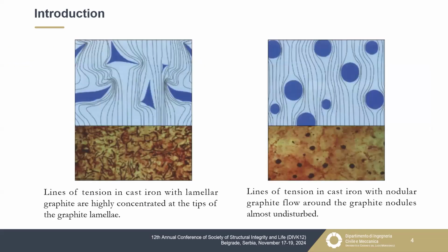Considering the graphite shape, it is evident that between lamellae and nodules, nodules are better, because considering lines of tension, we have a concentration at the crack tip of graphite lamellae. Instead, in graphite nodules, we do not have this problem. And if we compare, for example, the stress strain behavior, we know that lamellar cast irons are worse.